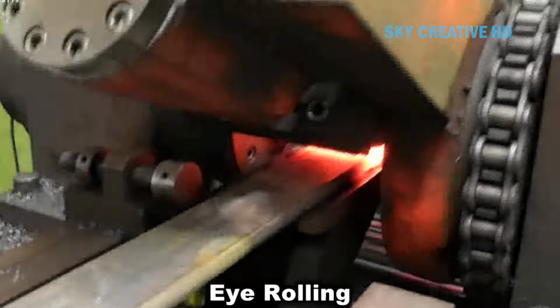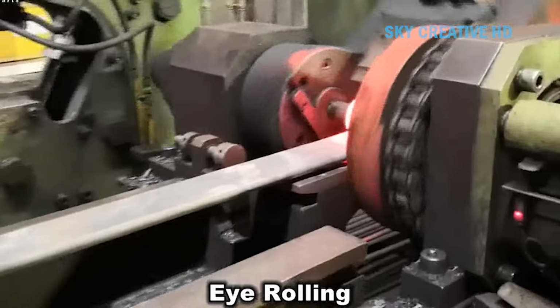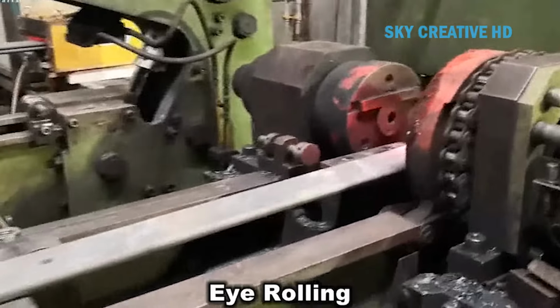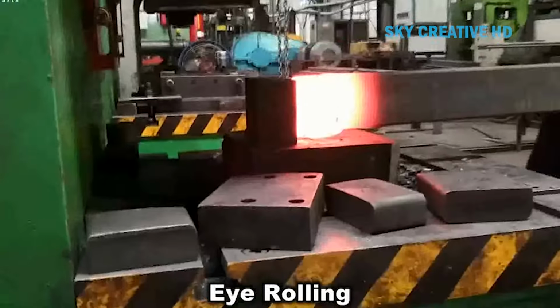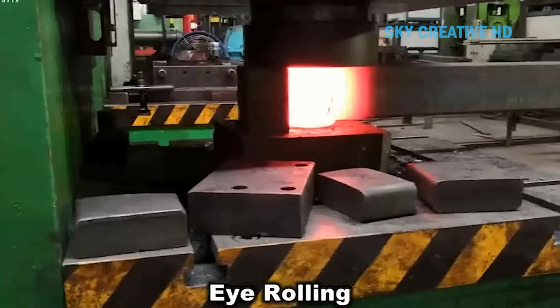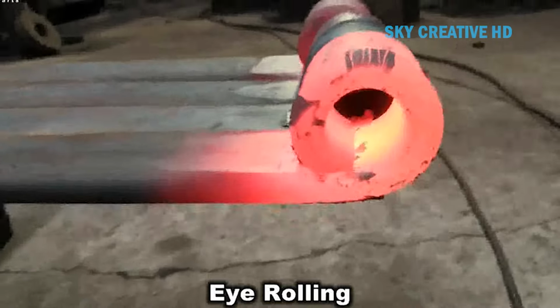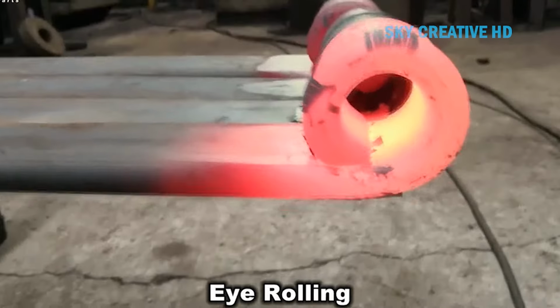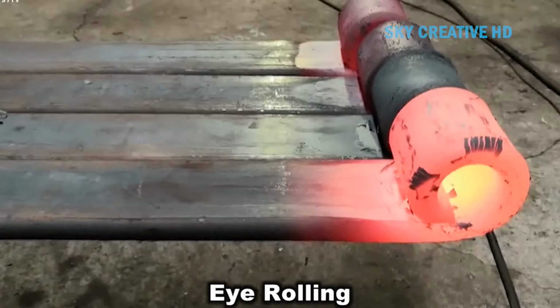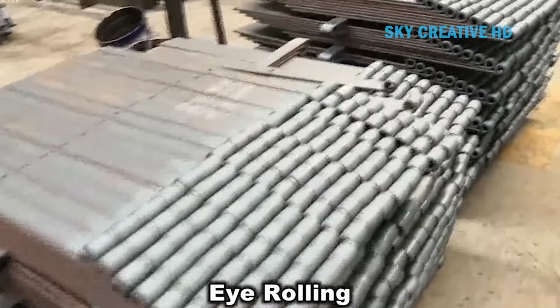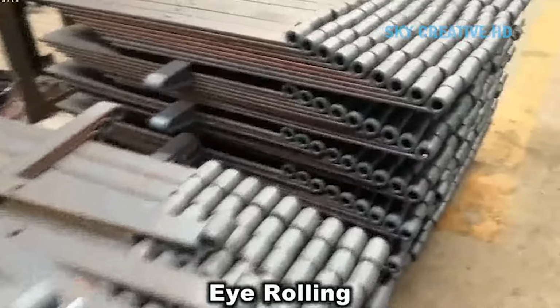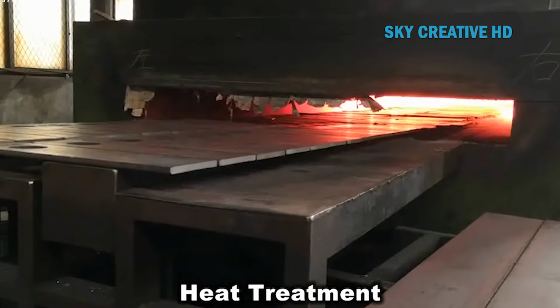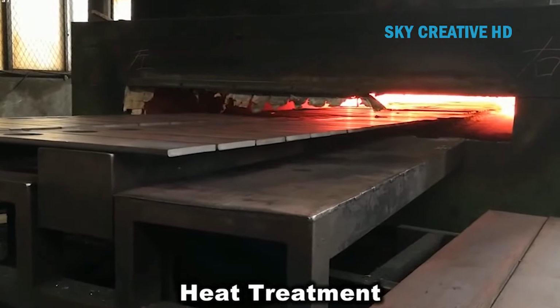But here's the clever part. That's too hard for practical use. So the springs immediately go into tempering furnaces at lower temperatures, around 800 to 900 degrees Fahrenheit. This tempering process is the secret sauce. It relieves internal stresses and adjusts the hardness to achieve the perfect balance between strength and flexibility. Hold it too long or too hot and you get soft springs that sag. Too little tempering and they'll be brittle and crack under stress. Wondee's metallurgists have perfected these parameters through years of experience and testing.